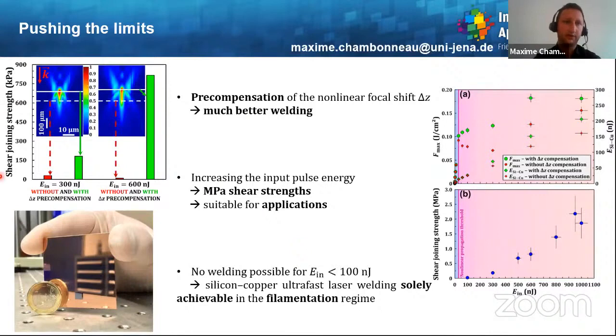Here on the left, you can see the shear joining strength represented as a function of the input pulse energy, for two cases actually: without, in red, and with, in green, nonlinear focal shift precompensation. And it is pretty clear from this figure on the left that precompensating the nonlinear focal shift delta Z leads to a much better welding. Okay, so what now if we decide to increase the energy even more, but at the same time precompensate the nonlinear focal shift delta Z?